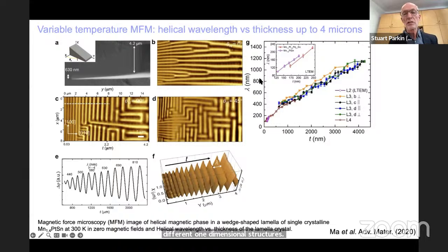And what we found, on the right-hand side, you can see that the wavelength of this helical structure increases systematically as the thickness of the lamella in which we're imaging these objects is increasing by more than a factor of 10, from 100 nanometers for the thinnest layers, where we could use Lorentz microscopy, to more than a micron for the 4-micron thick layers. And these are giant objects, more than 1 micron in size, that we can then detect optically as well.